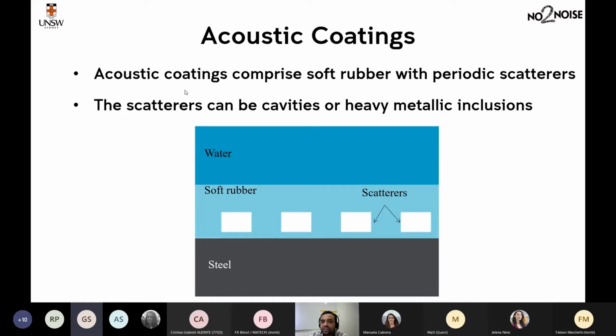So to fully utilize the shear damping in soft rubber, you include some scatterers in your material, and those scatterers scatter the sound in different directions, and they convert your pressure waves or longitudinal waves to shear waves, which are efficiently absorbed in your coating. Two most commonly used types of scatterers are cavities, just cavities in a soft rubber, or heavy metallic inclusions, for example,